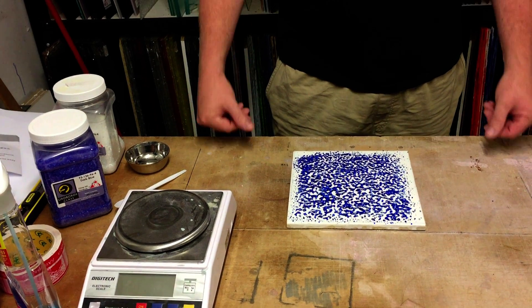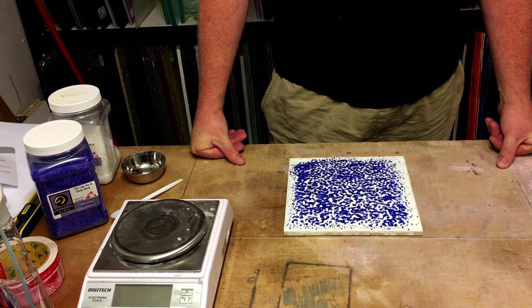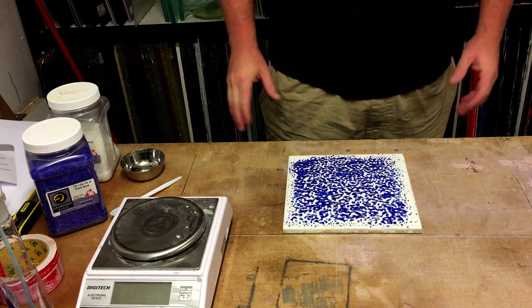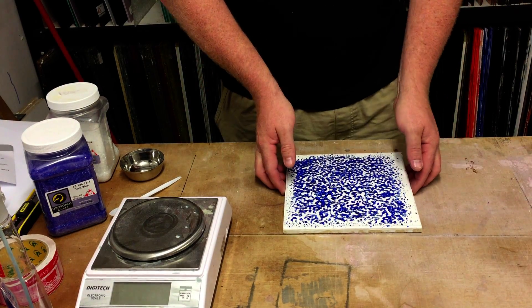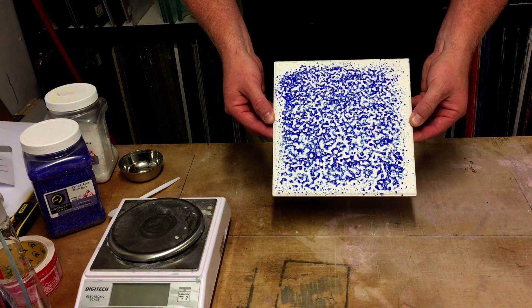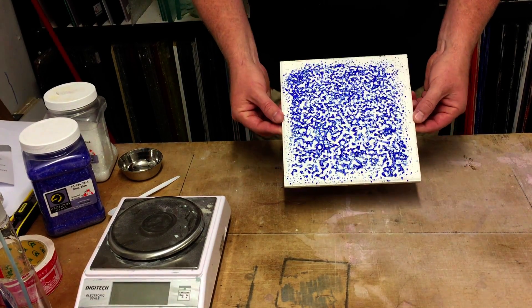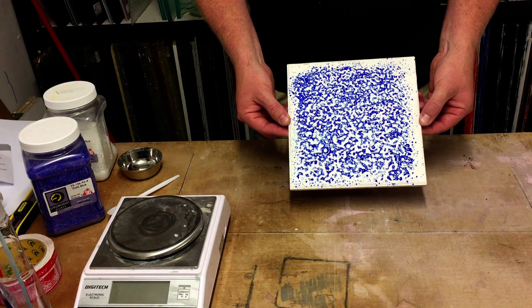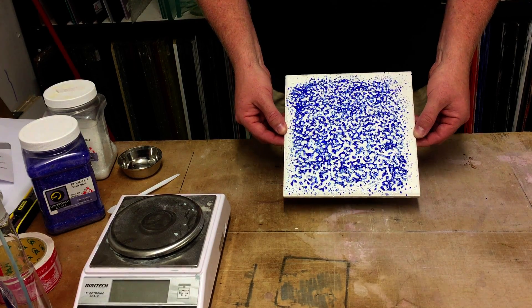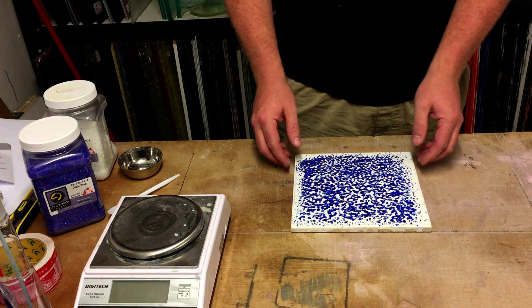Today is now tomorrow — the firing finished up at about seven o'clock last night, but we were busy doing a complete clean out of one of our children's bedrooms, which was drastically overdue, so we left it until today. As you can see, it's had quite a nice little fusing. We've got quite a lot of nice laced sections, and also several small sections which we'll use for pendant jewelry. This was our 2 gram per square centimeter amount of glass. If you want it to open up with bigger holes but have everything still connected, you can go up to about 4 grams per square centimeter. I might actually build one of those as well, just so you can see the difference.